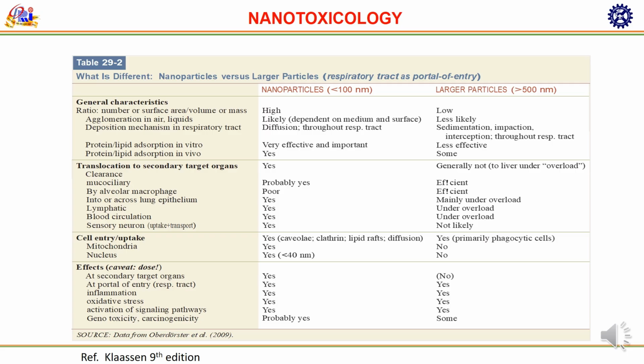Translocation to secondary organs and clearance. Nanoparticles are more likely to translocate beyond the lung into the bloodstream and other organs. Larger particles generally do not translocate unless there is overload in the lung. Mucociliary clearance: for nanoparticles, clearance may be slower but still occurs, and for larger particles it is usually efficient via the mucociliary escalator. Alveolar macrophage clearance is poor for nanoparticles and efficient for larger particles. Across the lung epithelium, nanoparticles can penetrate and enter circulation. For larger particles, this happens mainly under overload conditions.